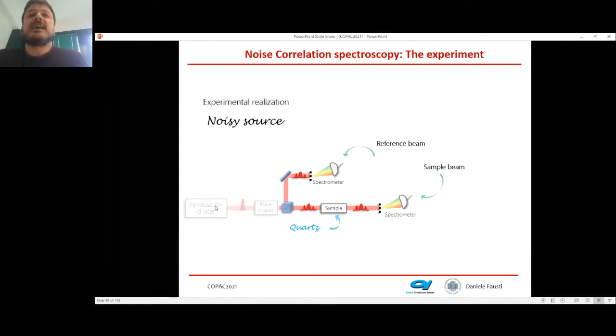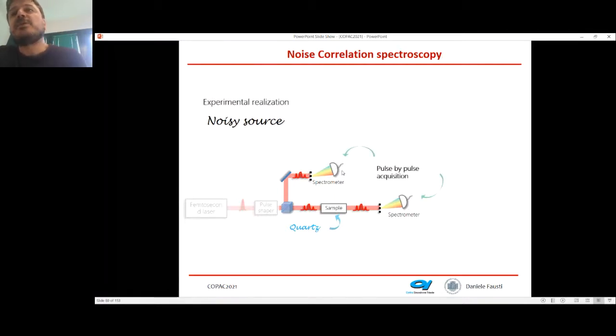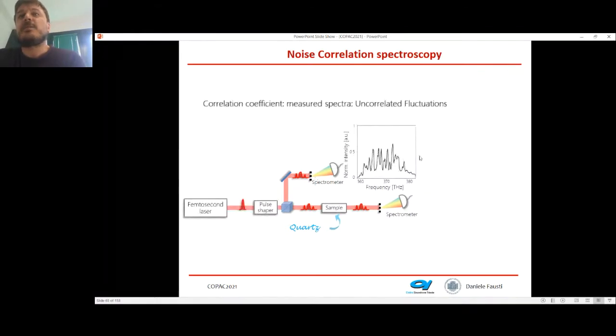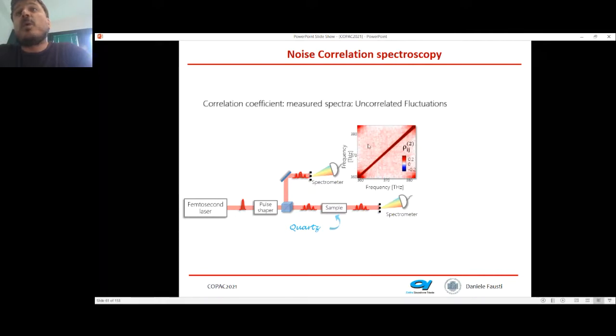We developed a laser source where we could introduce frequency uncorrelated noise, just with a pulse shaper, I spare you the detail, and then we do single shot measurements for these pulses and we just acquire them like here. The animation here is data, where I show that the spectral content of every single pulse is completely different, and the fluctuations are as random as my random number generator. So every spectroscopist in the room will tell you that it's impossible to measure with this kind of laser. But if you look at the correlations, it looks exactly like the correlation that we wanted, because one frequency correlates only with itself, while there are no correlations between frequencies which are different. This is the white spectrum here.